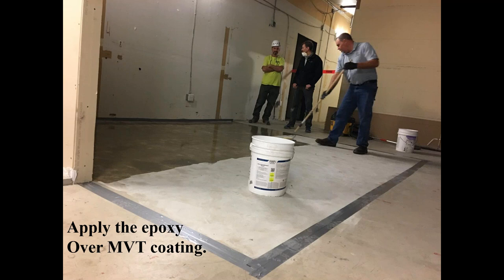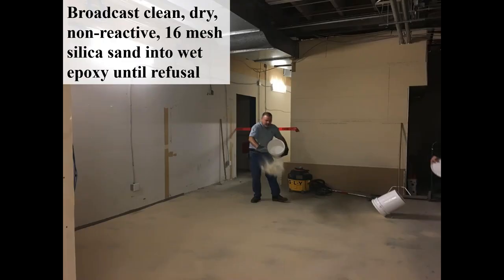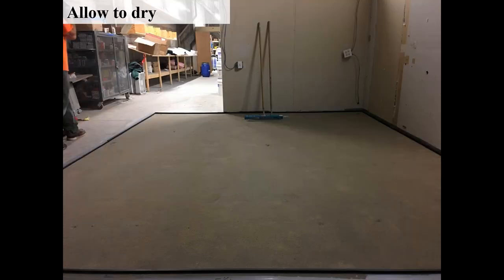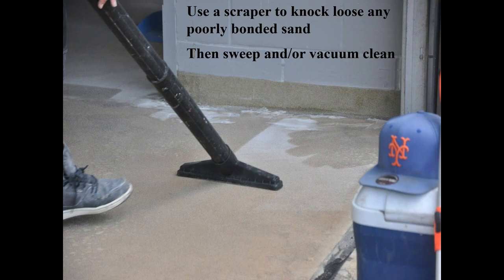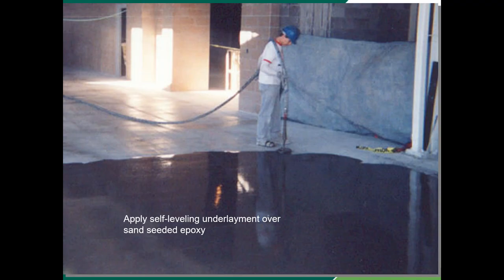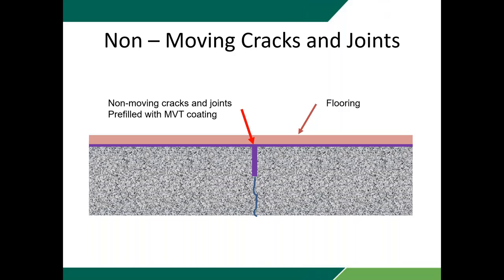So what I'm talking about here is they're putting down an epoxy primer over the top of the moisture vapor transmission coating. They're sanding it to refusal. They come back and they remove all the excess sand. And now you've got this nice mineral surface that I can put my underlayment over, and the underlayment bonds to that. And now, once I've got that underlayment, I've got a cementitious system that they can come in and put that tile adhesive down over.